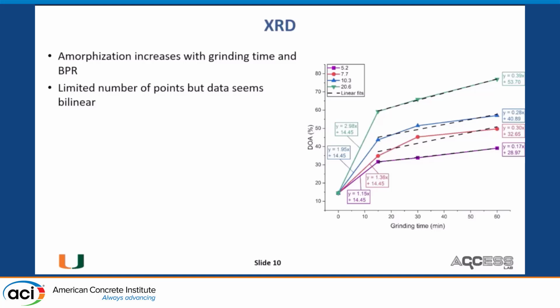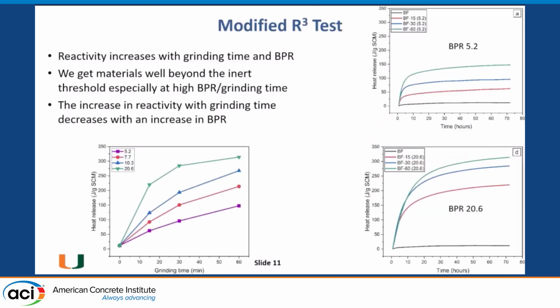So we said, okay, all of this is great, but are these actually useful materials? Are we actually making them reactive? And the good news is we absolutely are making them reactive. So we did a modified version of the R3 test, pretty similar to the R3 test. It's not going to make a big difference in this context, but we see very clearly that as the BPR increases and the grinding time increases, the reactivity increases.